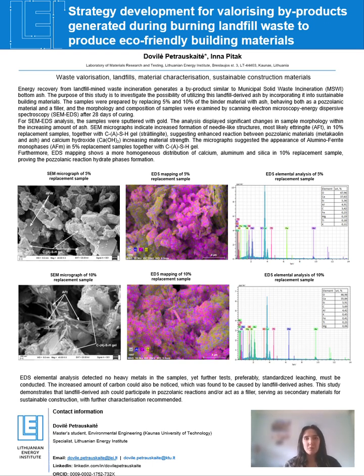So in the 10% replacement sample, the microstructure becomes more pronounced, and we can observe needle-like crystals typical of AFt phases, mainly ettringite, along with more extensive C-S-H gel formation. And this suggests stronger interaction between metakaolin, ash, and calcium hydroxide, leading to more complete hydration. So this richer microstructure could enhance material strength because the gel fills pores and binds particles more effectively.